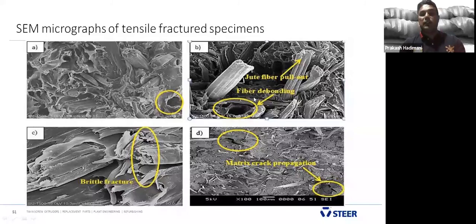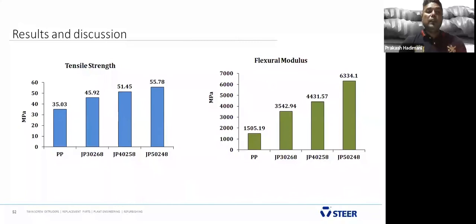In some of the standard samples, we saw the jute pulling out from the polymer matrix, which we call fiber debonding and fiber pull out. We observed a brittle fracture in some of the fibers because the polymer wetting was very bad. That shows the brittle fractured surface. If you see the results and discussion on tensile, for the virgin polymer we observed 35 megapascal, and the addition of 30% slowly increases the tensile strength. At 50% we observe 55.78. So it is a good tensile strength compared to other wood powder and all. Jute is giving better tensile strength.